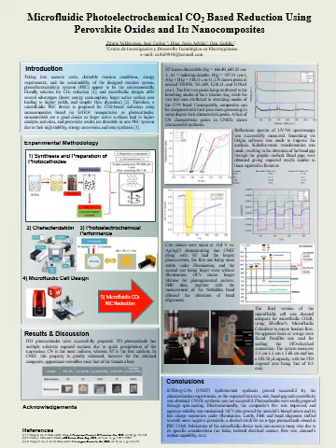The obtained values are very close to those reported in literature, so this is also a good sign that the composite synthesis has the right composition, structure, and light absorption characteristics that were sought. After this, photoelectrochemical performance followed using a solar simulator, which worked at spectra of AM 1.5 G with an intensity of 1.1 suns, and the ITO photocathodes were placed in a 3-electrode configuration using potassium chloride 0.1 molar as its